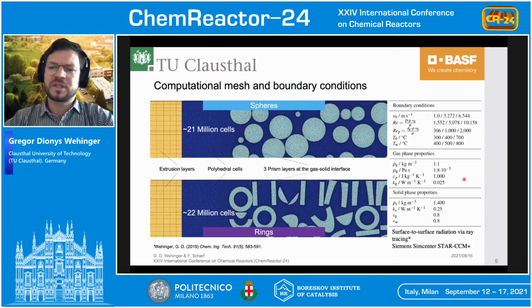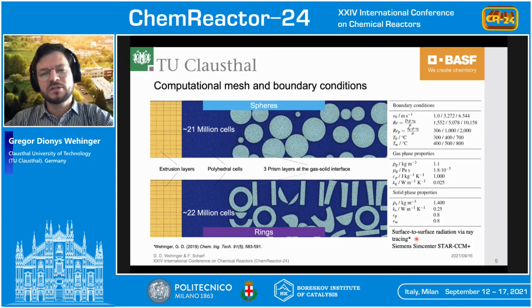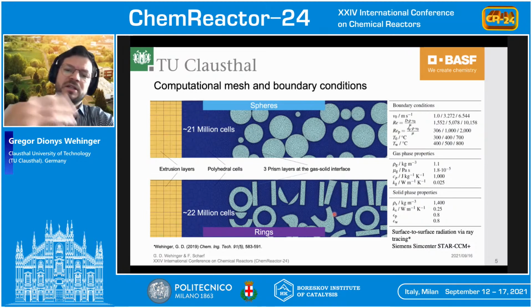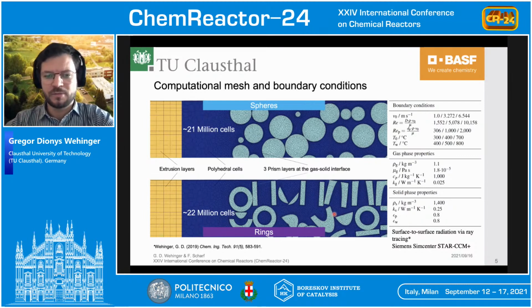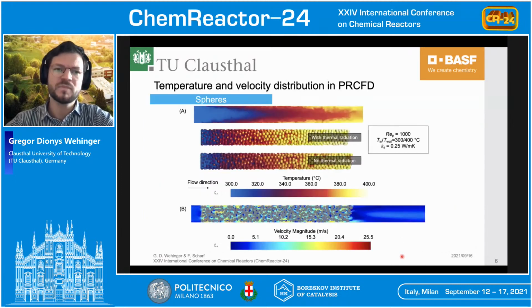And then we kept the gas phase as well as solid phase properties constant, just in order to better compare the results. Surface to surface radiation was then taken into account. So that means the solid particles irradiate thermal radiation to neighboring particles with the so-called ray tracing method included in Siemens SimCenter Star-CCM+. So let's go to the results.